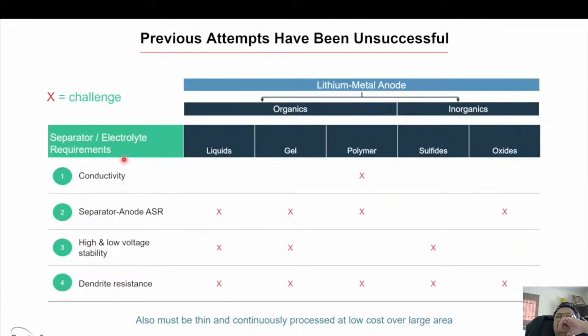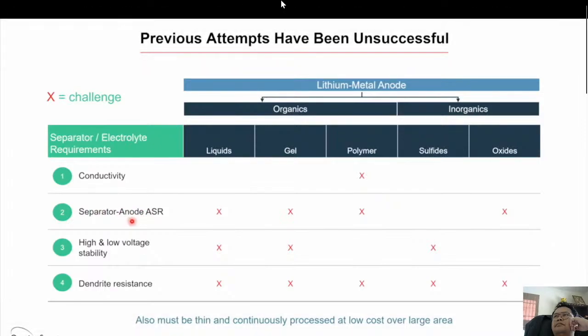So when it comes to the separator, some of the key requirements, at least in the automotive space, are it needs to have a high bulk conductivity, competitive with liquid electrolytes. If you think about it, it's pretty impressive to have lithium hopping through a solid matrix as quickly as it'll transit through a liquid, but it is possible in some materials. Then the interface to the anode needs to be as conductive as possible.